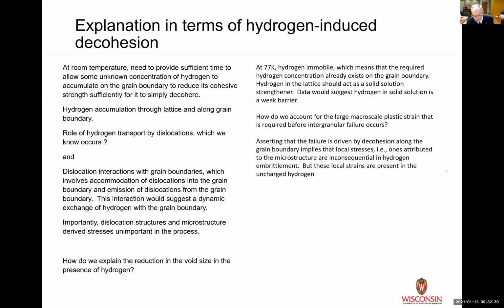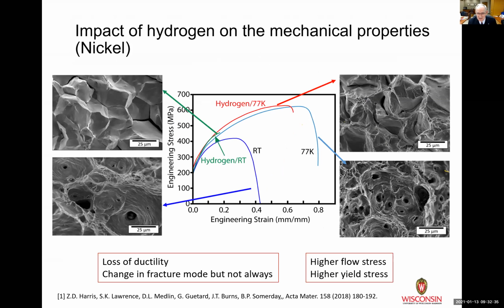I'm going to see if I can go back in slides, which is something I normally don't do in a talk. But let me go back and show you this. And here's the question I want you to think about. At 77 Kelvin, we said that all of the hydrogen should be on the boundary because there's very little diffusion that's going to happen either through the lattice, along the grain boundary, and there's going to be very little transport by dislocations. So the hydrogen concentration that's on the boundary at the beginning is the one that caused the decohesion. If that's correct,